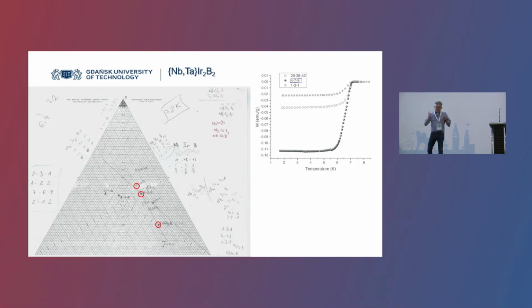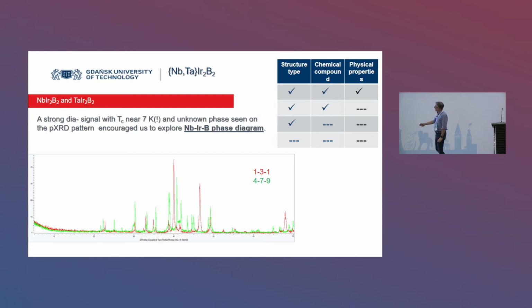And what you do, you compare the X-ray diffraction patterns, and also, and that's actually even more important, you compare magnetization. This is the normalized magnetization. You see it's emu per gram. And you can clearly see that the strongest signal is here. So is it 479? Maybe. And here is the X-ray diffraction of the 479. You see that those impurity peaks now are much much higher, and the main phase, which was the cubic phase, is actually gone, almost completely. We tested more and more samples, and this is the fourth strategy.